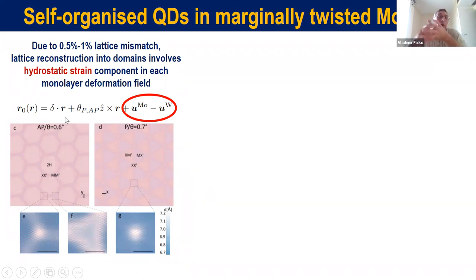We need to compensate this difference by hydrostatic strain. And then what happens is that over large areas of domains, the hydrostatic strain in each layer is small, lattice constants adjust to each other, but the remaining or the missing material has to be squeezed or taken from the domain walls. And in the domain walls, we get the largest effects of the hydrostatic strain. In fact, the largest appears to be in the domain wall network corners, in particular around these places where the local lattice structure is least energetically favorable. These are the places where the dichalcogens appear on top of each other.